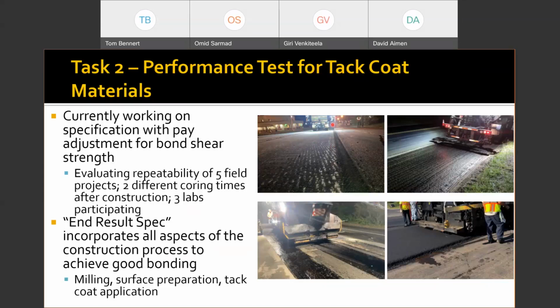Usually there's some water involved, and all this has to be removed or the bonding is just not going to be there. On the right side here, you've got a construction practice. Here's our tack coat, and you can see it's not necessarily evenly distributed. In fact, we get what we call ribboning, which is these longitudinal streaks where we get just a little bit of material coming out of the back of the distributor truck. In that case, we're not going to get enough material down to provide a good bond. Essentially, we've got not enough glue.